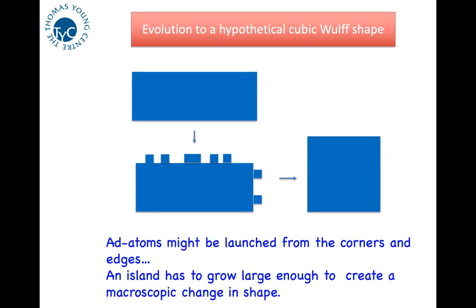Well, I think this is where simple diffusion is going to have to be helped along. Because here's a hypothesis. Adatoms might be launched from the corners and the edges of this object, and then they might diffuse around. But of course, thermodynamics, statistical mechanics tells us their densities are going to be the same everywhere on average. The only way it can find the Wulff shape is if it forms islands. So this becomes a nucleation and growth problem of islands. And the islands have got to become as big as a facet before it says, oh, look, I'm now in a slightly more cubic shape. I think I'll stay there and move on. So it'll evolve towards the cube by successive nucleation and growth of islands, I think. I don't have any evidence for this, but I don't see how else it could work.